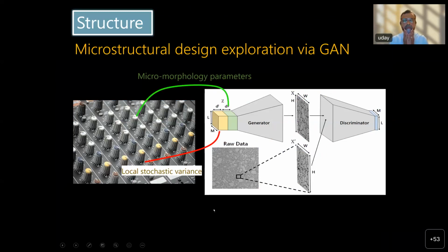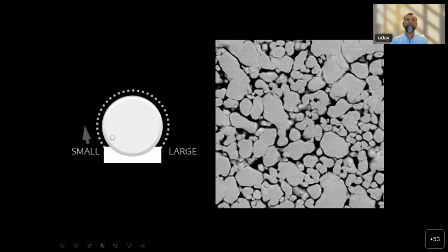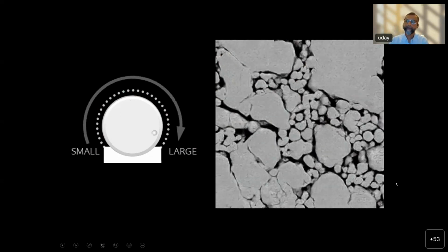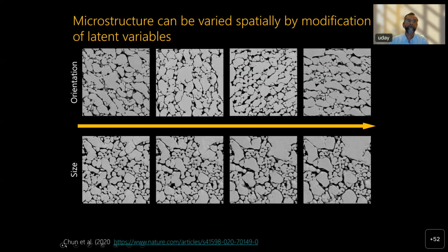Now, what that allows us to do in a materials by design standpoint is that we can manipulate the microstructure. So once we have the baseline microstructure that emulates the real microstructure, then we can turn knobs literally in the generator. Basically, we are modulating the latent variables, and by modulating the latent variables, we can change the structure of the material. So, for example, just to show one instance, by performing a particular operation here, we go from this initial small grain size microstructure, and we can manipulate the latent variables to go finally towards a larger microstructure. And we can do this for various other things as well.